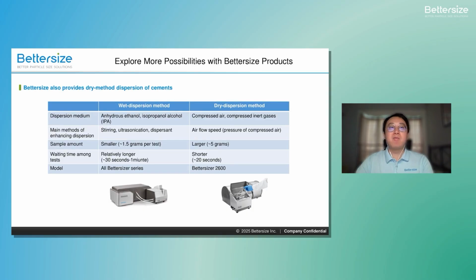The waiting time for cleaning the whole system between the tests is significantly shorter in the dry dispersion method, around 20 seconds. This dramatically increases your sample throughput, allowing for faster feedback on the product line. So, the choice is about having the right tool for the right job. For detailed analysis, use the wet method. For fast, high-volume quality control, the dry method is your solution for speed and more representative results.